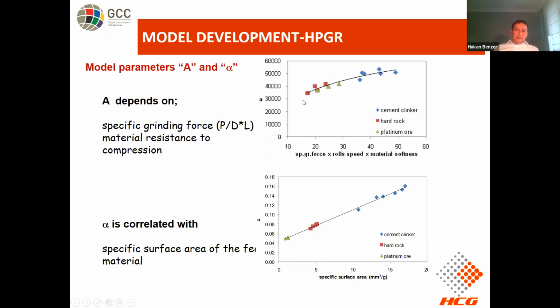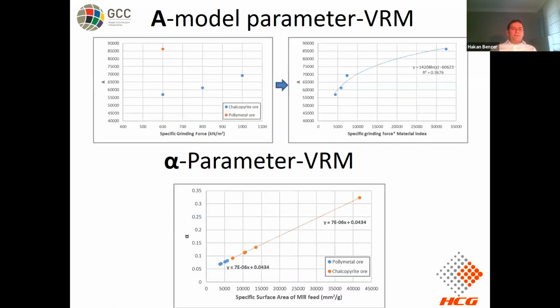But if you look at the line here, the lower end, because of the lower specific grinding force, comes from the hard rock application. And for the cement clinker, we have higher specific grinding forces. But at the end of the day, everything lined up on the same line. So we were able to model the HPGR by using this. The same approach has been taken for vertical roller mills as well.